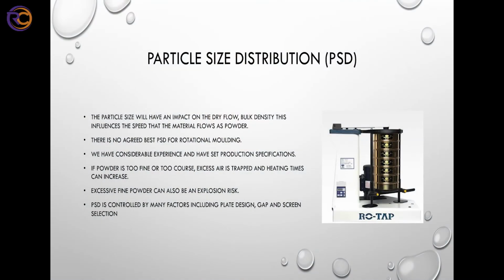So the particle size is controlled by a few factors. Plate design, by the change in your teeth you can change the particle size distribution, the gap and the screens. And also, if you don't maintain your mills and you're not changing your plates on a regular basis, a blunt set of plates can give you more fines.